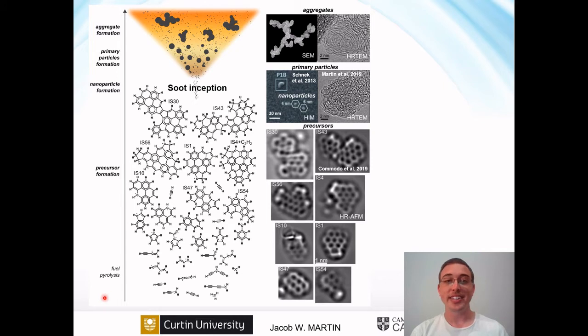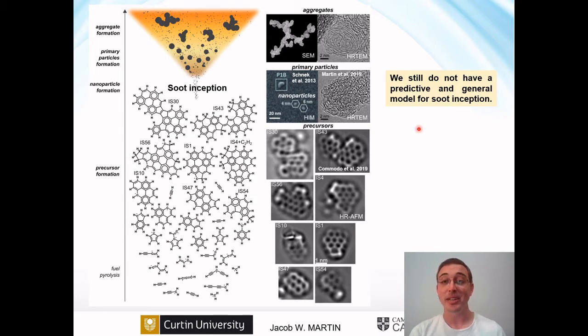So this is a schematic of how soot is formed from fuel. The fuel, heated up by the flame, degrades into these pyrolysis products, which then cyclize into ring species and grow with acetylene being added to these large aromatic molecules. And at some stage, soot is incepted, which means the molecules cluster together and form particles. And importantly, we still do not have a predictive and general model for this process. And this is significantly problematic because we don't really know how to eliminate that soot being produced or tune the properties of new carbon nanomaterials.